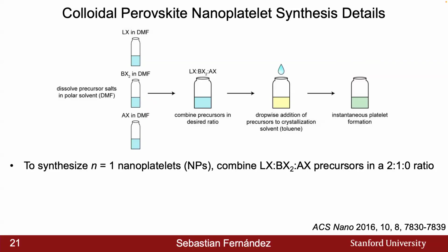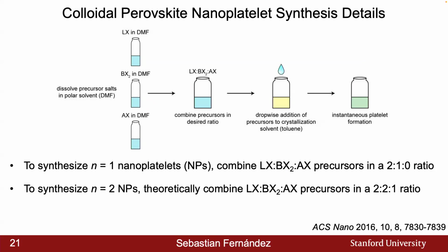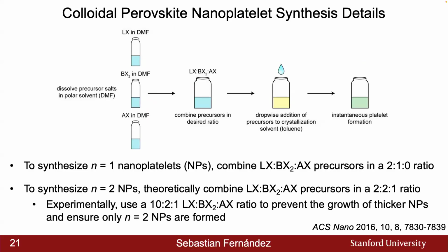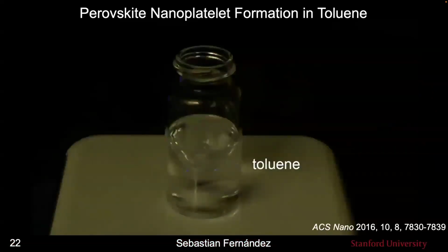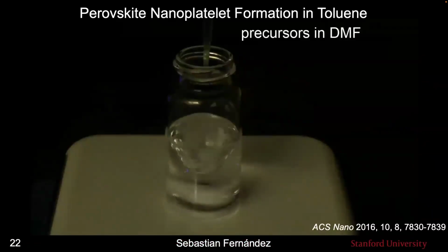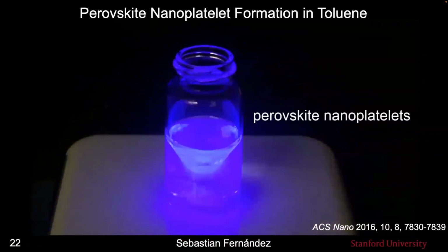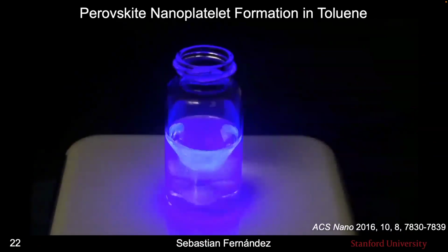So in theory, to make the n=1 nanoplatelets, we would combine the ligand, metal, and A-site cation in a 2:1:0 ratio, so no bulk cation. In theory, to get the formula that we want for the n=2 nanoplatelets, we would do a 2:2:1 ratio in this case, but the authors found that we actually need a little bit more ligand, so a 10:2:1 ratio, to prevent the growth of any thicker nanoplatelets, those between n=3 and n=infinity, and ensure that only n=2 nanoplatelets would form. And so the way that this looks is that we have the solvent that is stirring, and once we drop the perovskite nanoplatelet precursors, we can see the formation of these materials immediately.